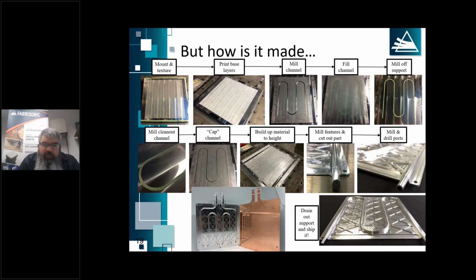Like all other 3D printing processes, we have a need for support. When we're welding, we're pushing down with a fairly high amount of force. So any channels wider than, say, about 1/4 of an inch, we're going to fill those channels with a water-soluble support material that's patent pending with Fabrisonic.